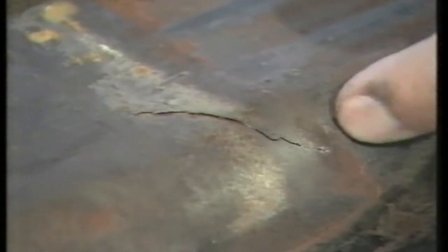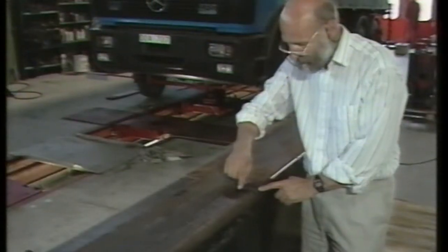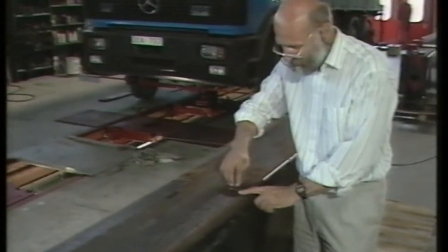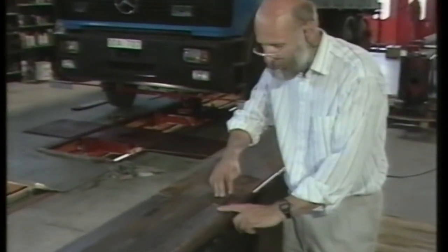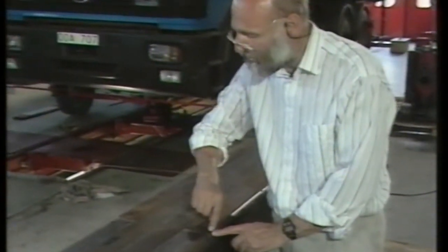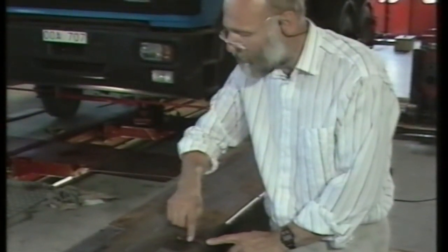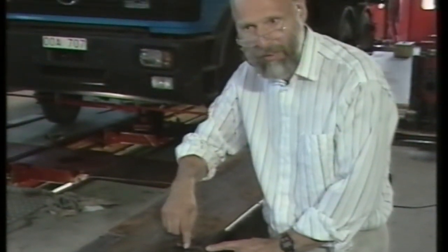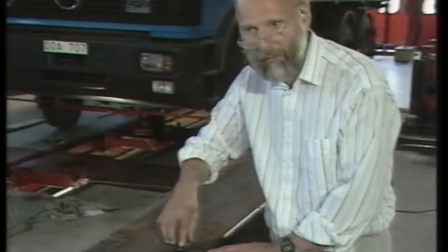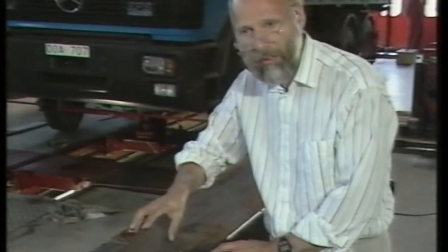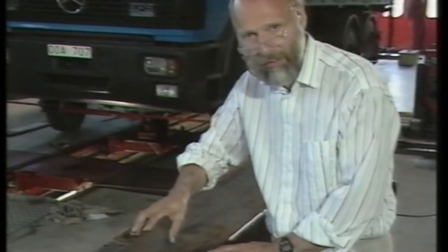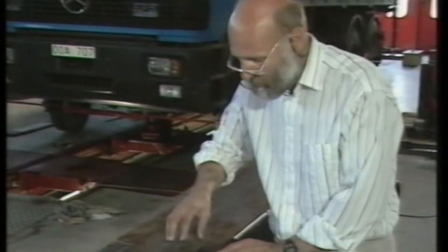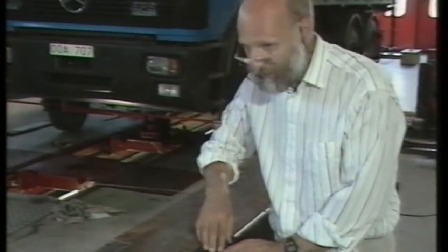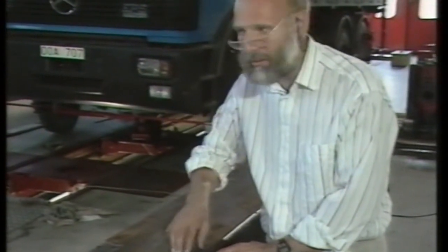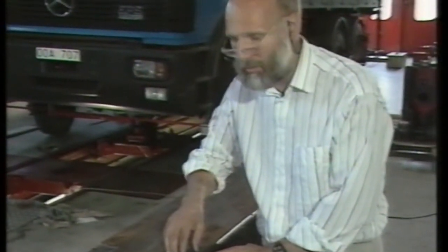Here we have a crack this long and is due to endurance failure in the beam. The supporting rollers have mangled the beam and deformed it. Deformation, plus the cracks, would have eventually led to breakdown anyway. This is due to the fact that the beam is undersized in respect to the supporting roller's pressure. It is because we dismantled the beam that the cracks were detected before there would have been a breakdown.